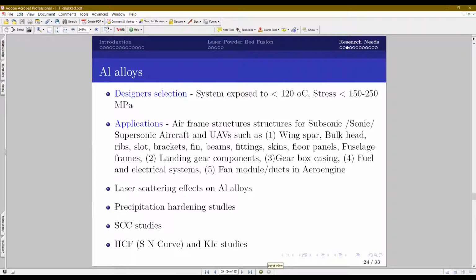So what are the research areas you can work on? Aluminum alloys are difficult to print due to poor absorbability, high reflectivity or scattering. So you can work on finding out the best laser which can give you better absorbability for the aluminum alloy. That one problem is very interesting.